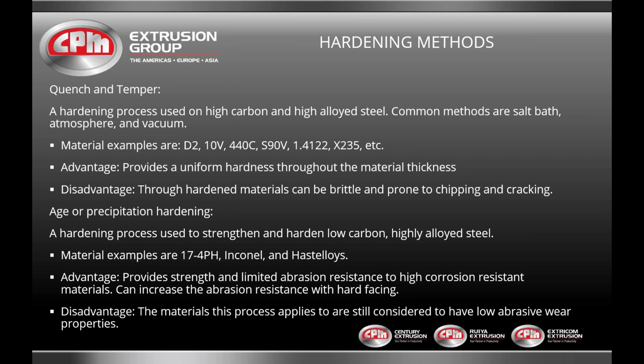Typically, we employ the salt bath or the vacuum, depending on which material we're heat treating. Material examples are D2, 10V, 440C, S90V, most of our through hardening steels. The advantage is they provide a uniform hardness throughout the material thickness. The disadvantage is through hardened materials can be brittle and prone to chipping and cracking.